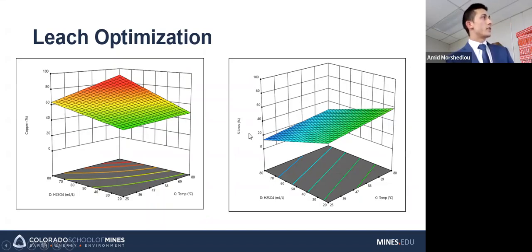On this side, we can see what the effects are for silicon. We can see that by increasing the temperature, we have a slight increase in silicon recovery. And by increasing the acid concentration, we get a decrease in silicon recovery. Now, that is not what you would normally expect if all we're using is sulfuric acid. In the data set used to create this, I also used a strong oxidizer, hydrogen peroxide. What that does at the higher acid concentrations or at lower pHs, it helps drive some of the silicon out of solution, which basically makes it harder to go into solution, right? Huge surprise.